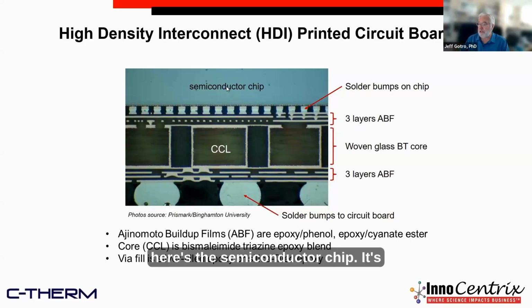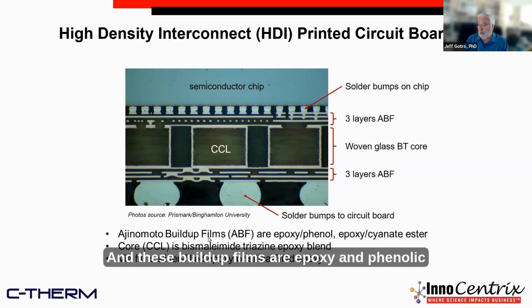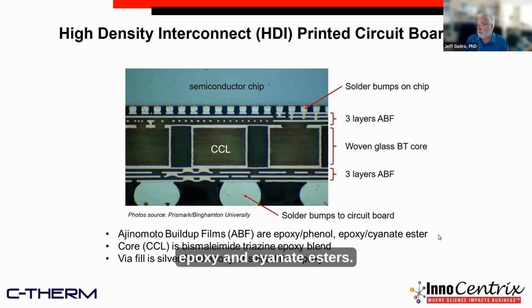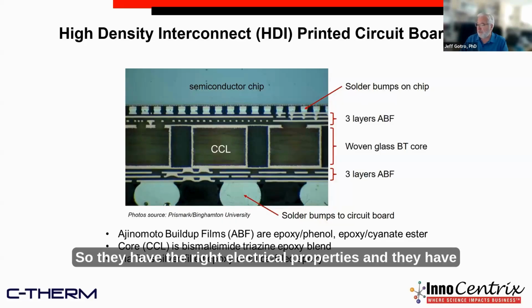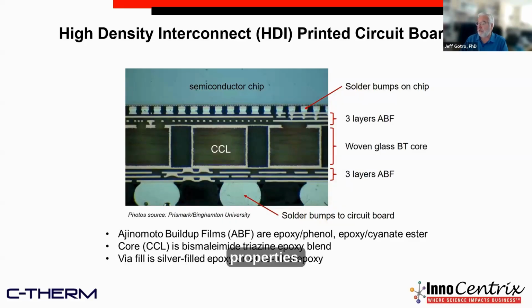And so here's a cross section of what we call a high density interconnect circuit board. You can see on the top, here's the semiconductor chip. It's got all these little connections, these pads that they solder ball down or pillar down to this high density printed circuit board substrate. So this is what's called a chip carrier. And then there's all these little interconnects through multiple layers of this Ajinomoto buildup film. And these buildup films are epoxy and phenolic, epoxy and cyanate esters. So there, again, there's a lot of chemistry that goes into developing these materials, so they have the right electrical properties and they have the right thermal and mechanical properties.